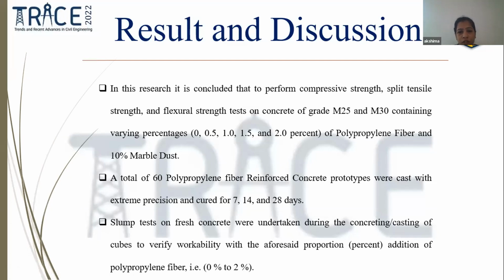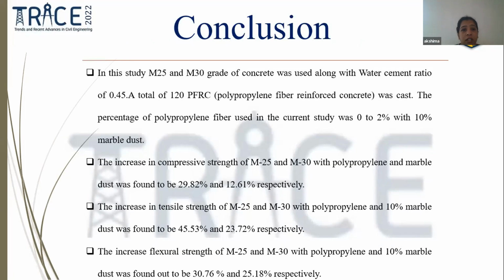Slump tests on fresh concrete were taken during casting to verify workability at the same percentages of polypropylene fiber, 0 to 2%, with an additional 0.5% each step. In this study, the water cement ratio is 0.45 and a total of 120 PFRC, polypropylene fiber reinforced concrete, specimens were cast. The percentage of PPF used in the current study is 0 to 2% with 10% marble dust, which is the main criterion of this research.